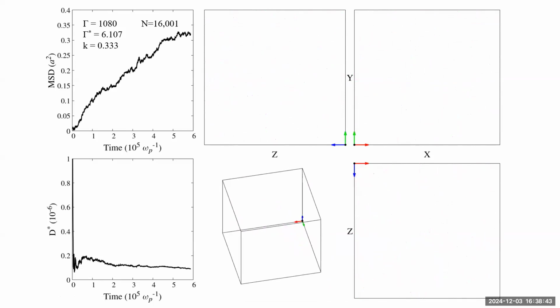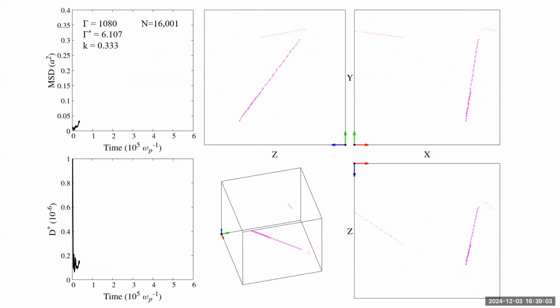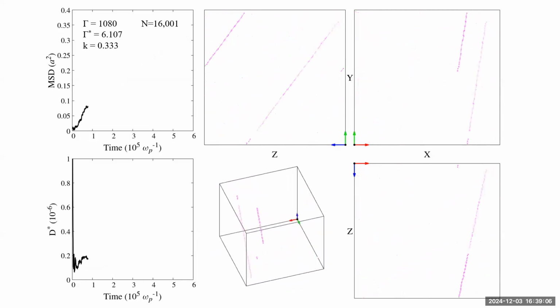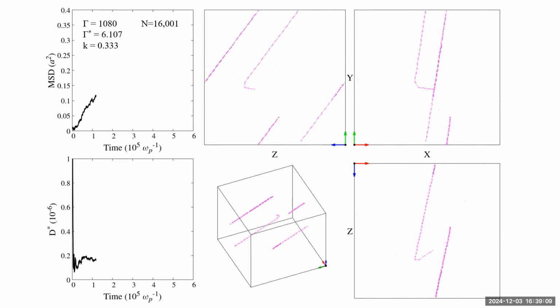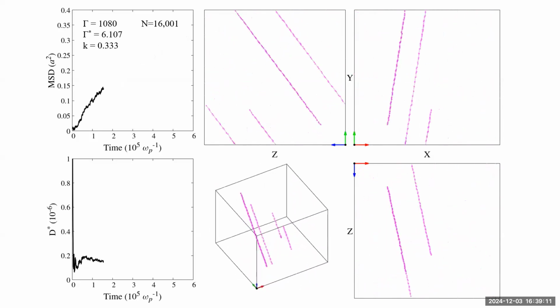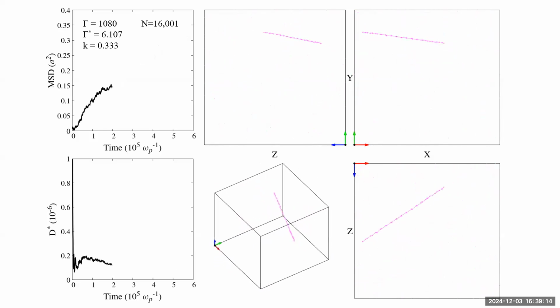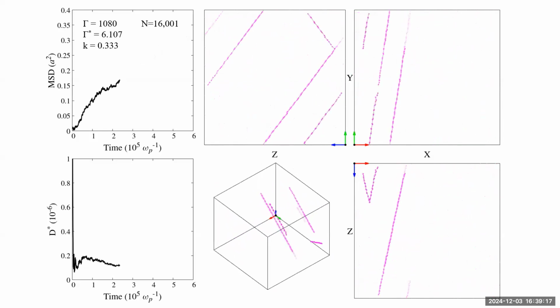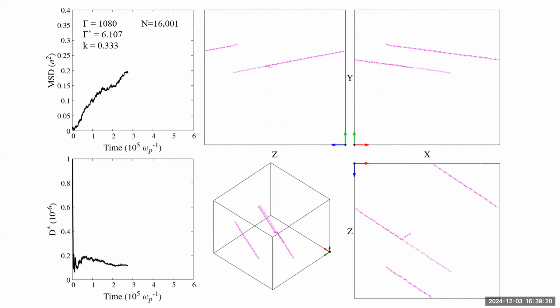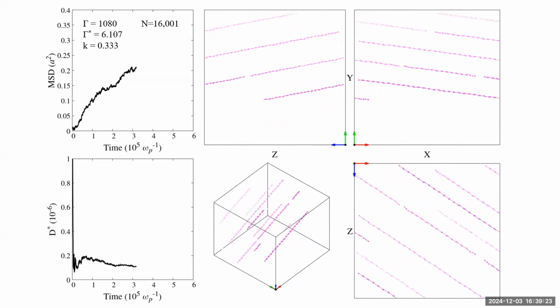But it tells you that even though interstitials and vacancies have different activation energies for migration in the crystal, an interstitial also has more than one activation energy. It has an activation energy for forward and backward motion, but then it has an activation energy for rotation and turning and moving a different direction on the lattice. And clearly, they are different and have different temperature dependencies. This is colder than those simulations I was showing you earlier, and we're seeing that the forward-backward motion is very easy now, while the turning motion is being quenched out. You're freezing out the turning of these defects. How neat is that? Let's go colder.